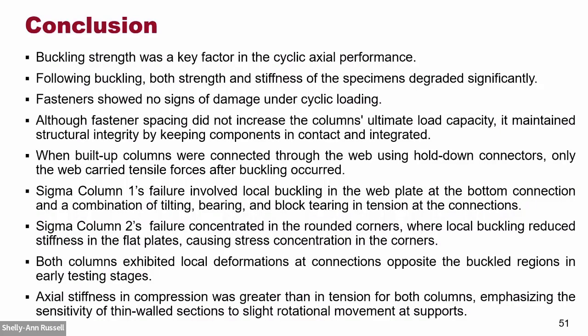Sigma 1 column failure involved local buckling in the web and at the bottom connection, and also a combination of tilting, bearing, and block tearing, as declared by the report they sent us. The sigma column 2 failure was concentrated in the rounded corners. Both columns exhibited local deformation at the connection opposite the buckled regions in the early testing stage. Axial stiffness in compression was greater than in tension. This is because the thin wall section has a slight rotation movement at the supports.